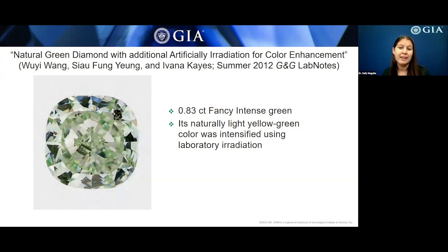The authors used the M3 intensity as an internal reference in order to make that determination. And so based on this, they believe that the color improvement from light yellow green to intense green was due to laboratory irradiation, and shows instances where a light green diamond can have that color enhanced using laboratory irradiation.